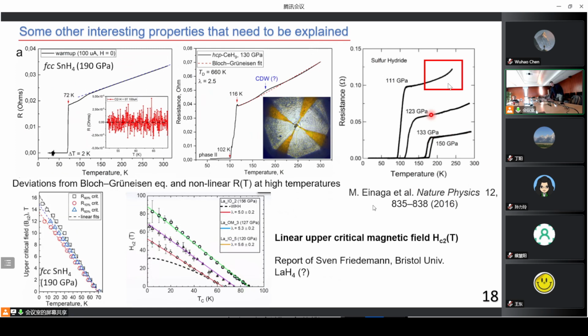I would like to also point out that there are several anomalies in the behavior of the upper critical magnetic field in tin hydride SnH4, cubic modification, at 190 GPa. The magnetic phase diagram is completely linear. There is no flattening, no deviation from the linear fit. And the same was found by Sven Friedemann from Bristol University. They presented several pulsed magnetic field measurements for LaH4, and the magnetic phase diagram for this compound is also completely linear, which is unusual.